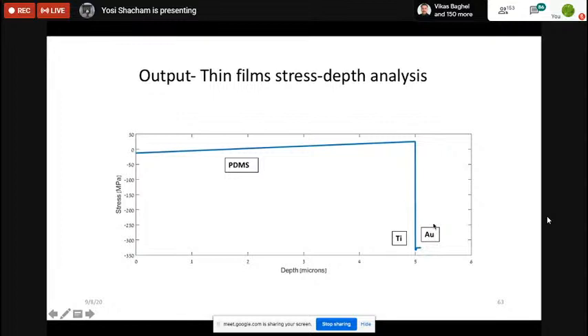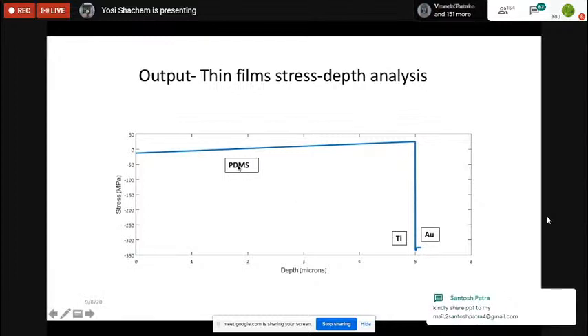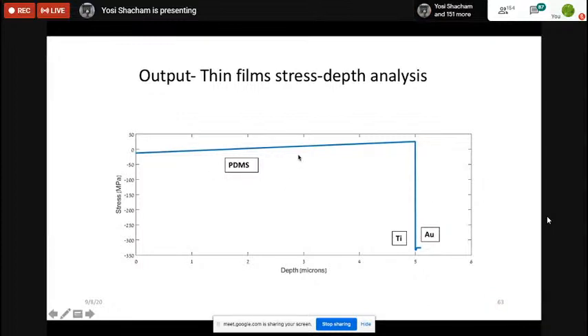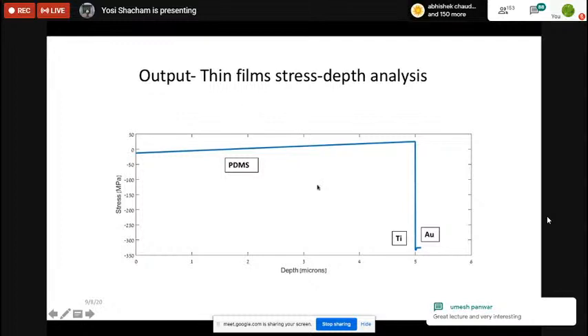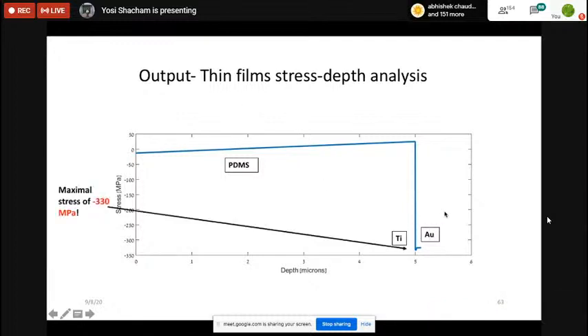But then, to our surprise, we got in the gold a stress of more than 300 megapascal, huge stress on the gold, which we did not expect. And what we found out is that PDMS is a very soft material, but it's incompressible. And the problem is the gold and the PDMS have different coefficients of thermal expansion. So when you heat them and cool them, the PDMS is applying a huge force on the gold.